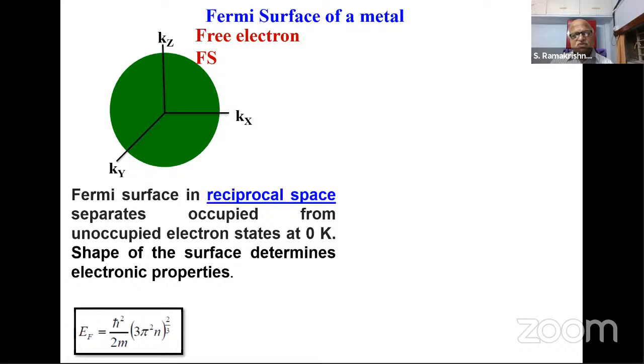So the Fermi energy is a function of the density of the electrons, and these are constants, Planck's constant as well as the mass of the electron, with n to the power of 2/3. So if n is small, E_F gets smaller. For metals, n is of the order of 10 to the power of 22, so E_F is of the order of 9 to 10 electron volts.